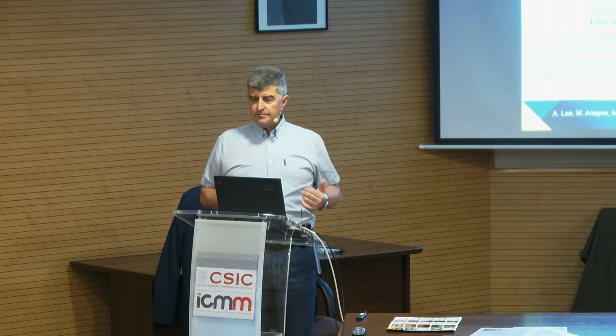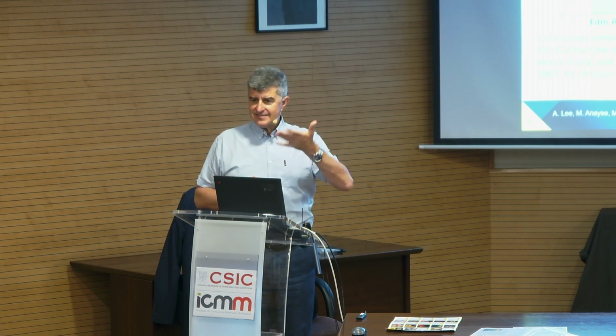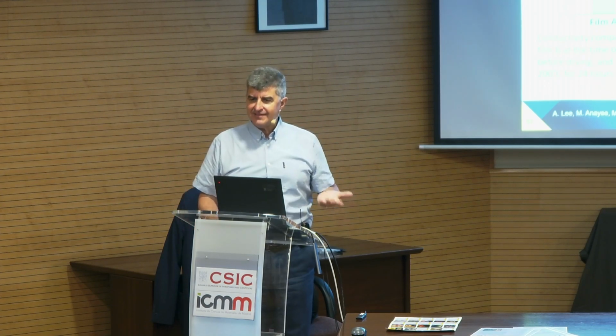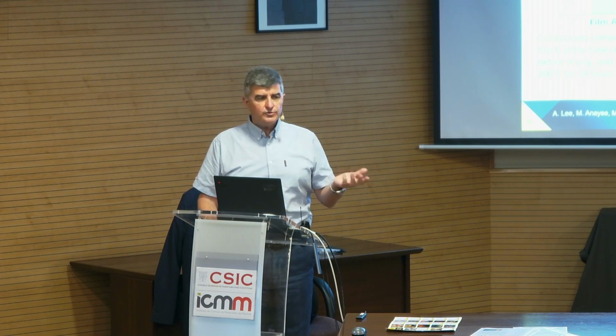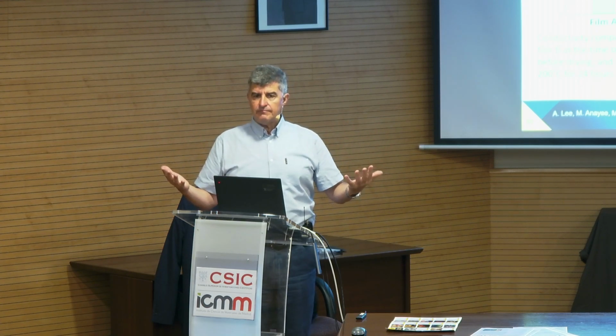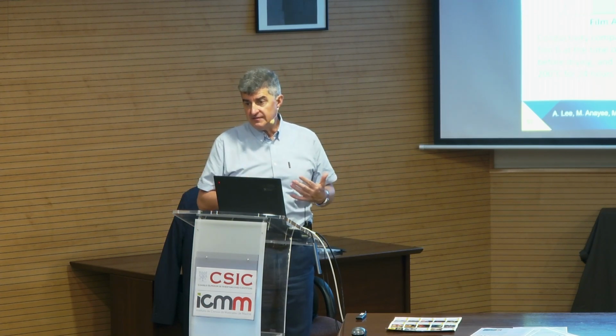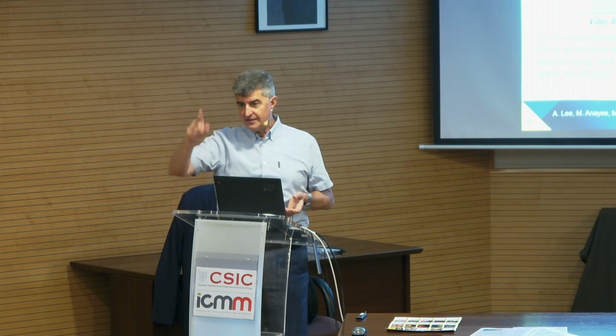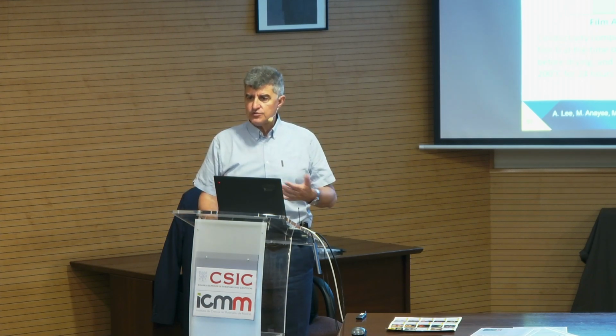We can actually, and we have done it, design the stability of the material on demand. For example, people who use MXene for lenses want to have them stable over a long time in a biological fluid environment. But people who use them for photothermal therapy or drug delivery don't want the particle to sit in the body forever. So what we can do is take the same MXene, but in one case make large flakes with as perfect structures as we can make today for stability. But then we can make the same MXene with basically the same absorption band, but with a lot of pinholes, defects, and non-stoichiometry in the X lattice, which will degrade much faster. So, for example, after killing cancer cells, it can pretty quickly degrade and be removed from the body through the liver and kidney as small titanium or niobium oxide nanoparticles. Thank you.